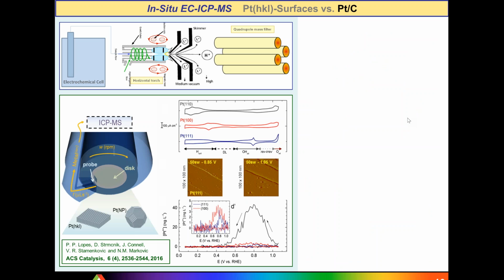And what we did is actually we managed to couple two methods. This is rotating disk electrode with inductively coupled plasma source, which ends with quadrupole mass detector. So that gave us extremely high sensitivity to detect dissolved metals from single potential cycles, and basically our detection limit was in the range of ppt. So to be accurate, this is parts per trillion, so extremely high sensitivity. And basically what you can see in lower portion of the slide, those are results from single potential cycles obtained from different single crystals of platinum.